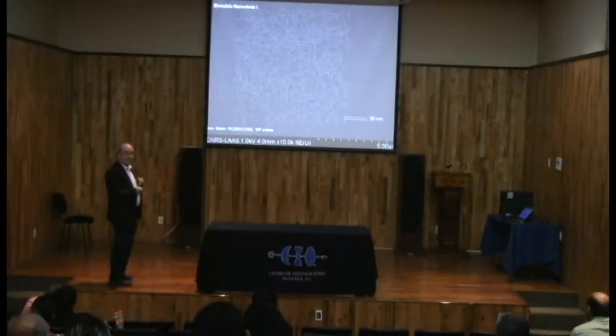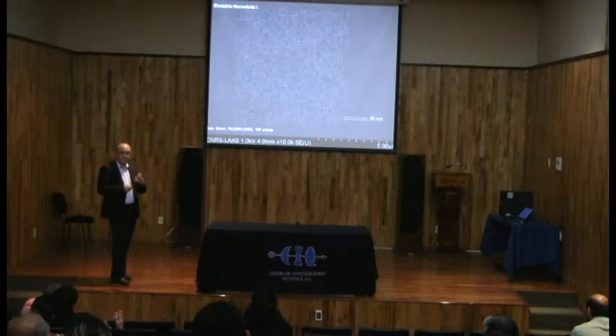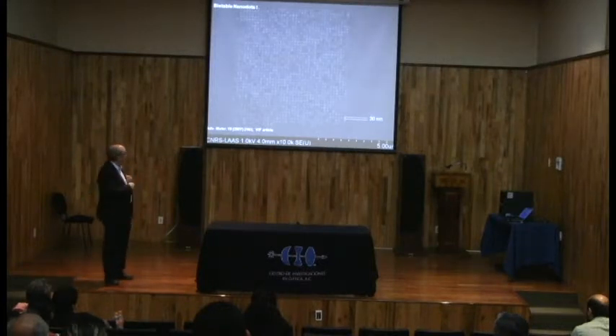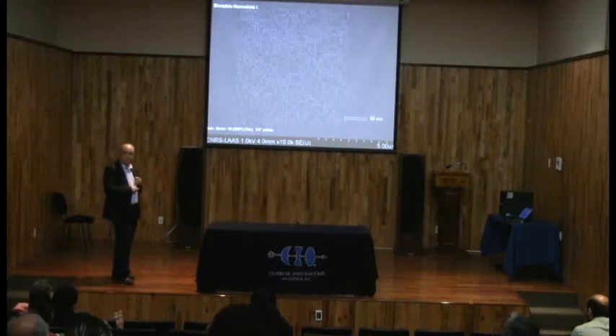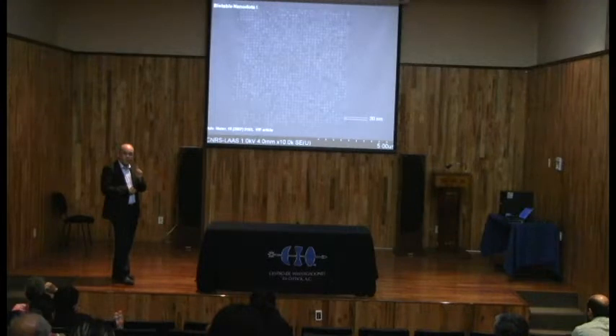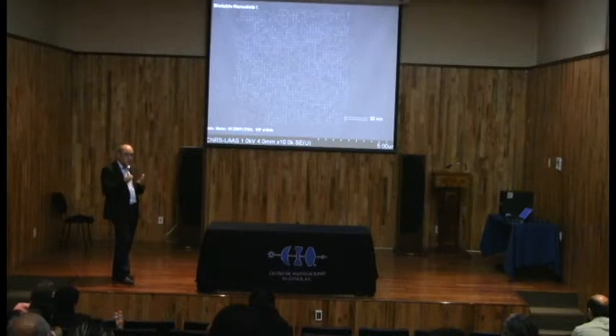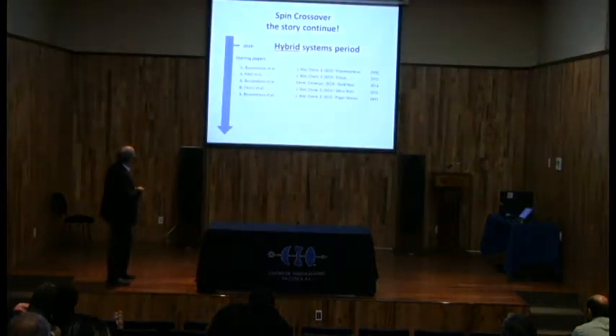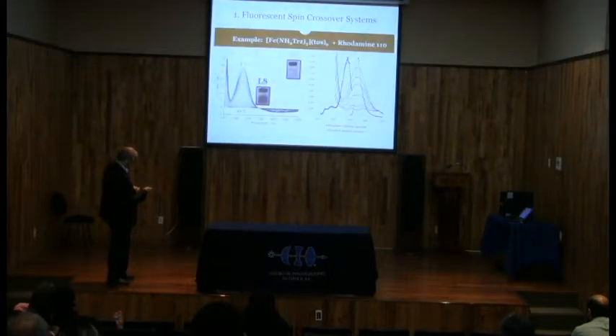And then the question for us was to see to measure what is the property of only one dot. Okay, you see in magnetism, one dot here, 30 nanometer dot here, switching between spin 0 and spin 2, the change of the magnetization is very small. This means that there is no machine can measure just one dot. Okay? So then we thought about what protocol we can use in order to measure the property of one dot. So then we used chemistry for this, and then the period, hybrid system period started, okay? And then the idea is the following.